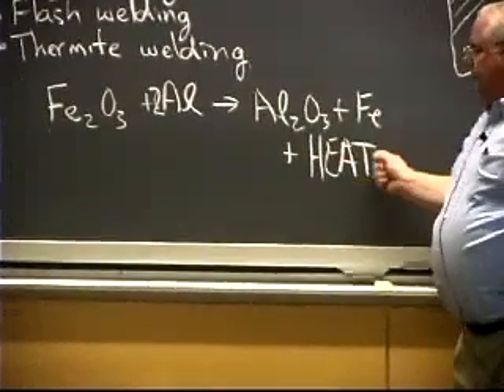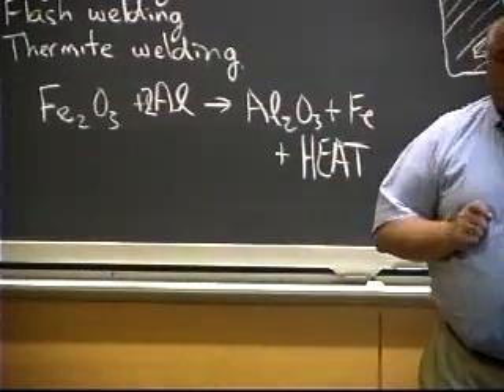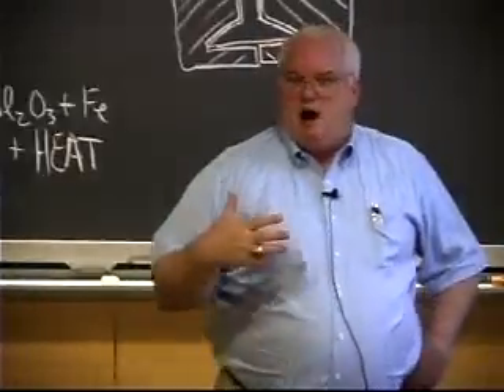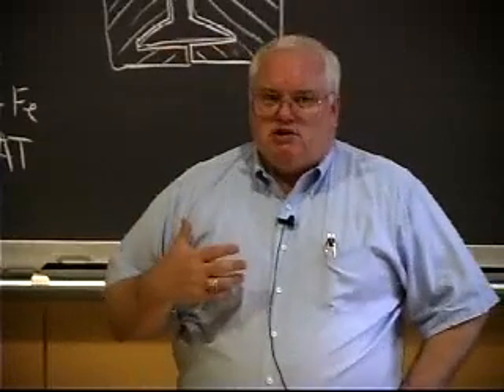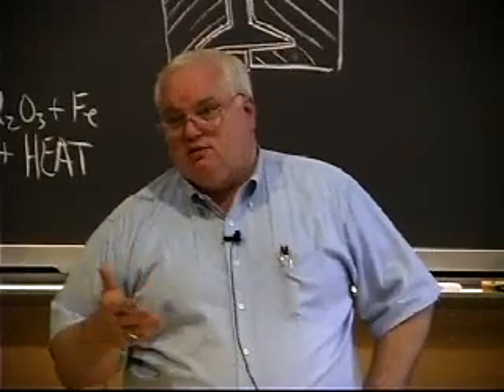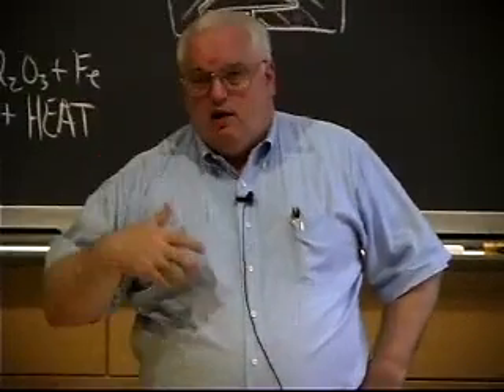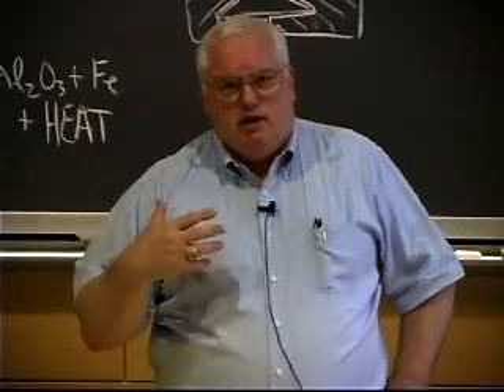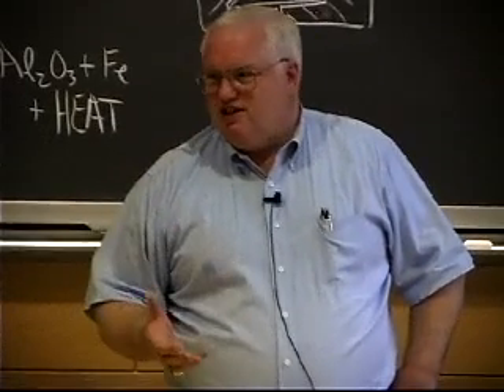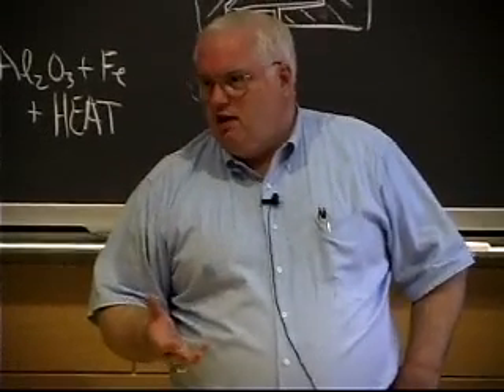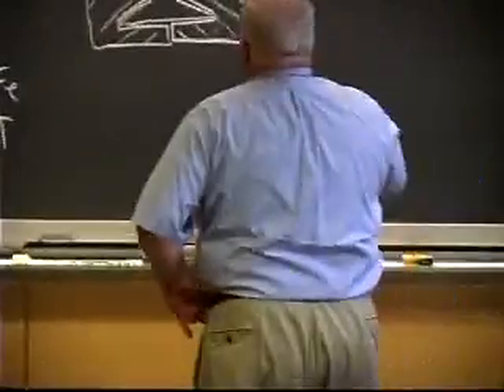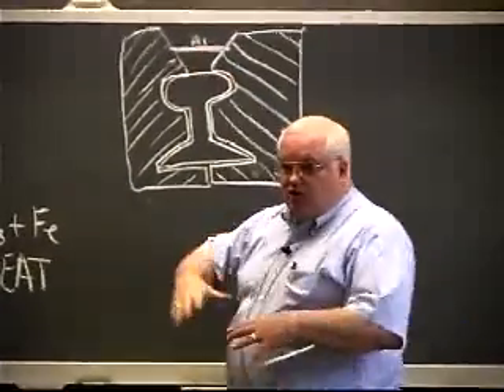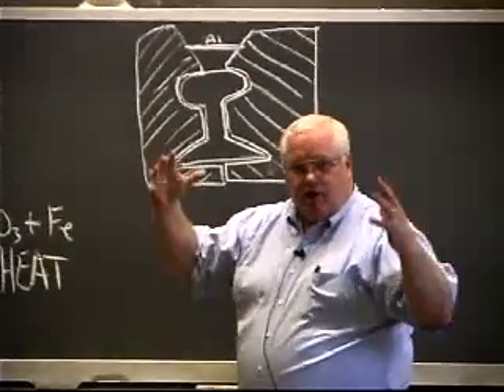Plus it gives off about 200 kilojoules per mole, which is enough to heat that iron up to 2,000 degrees centigrade. The steel only melts around 1,500 centigrade. So the iron is molten. It's got about a 500 degrees centigrade superheat. And of course, that molten iron, the thing goes off like sparklers on the 4th of July, okay?